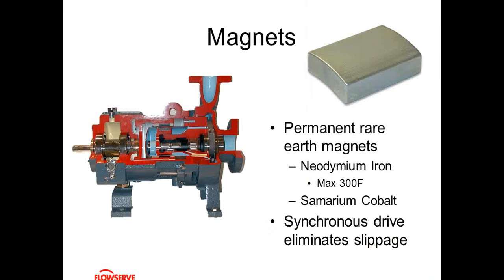All right, so we talked about the materials, the overall materials. Now let's talk about magnets. There's really two types of magnets you can use, here and here, okay? And that's just one magnet block, which is probably the size, I'd say, of a 2 by 4, okay? Neodymium iron is the magnet of choice, I'd say, in almost any industry. Neodymium iron is used, I say max 300. Some manufacturers would argue you can go up to 350, even 400 degrees, but I'm a little conservative. So once I get to 275, 300, then I move on to samarium cobalt.